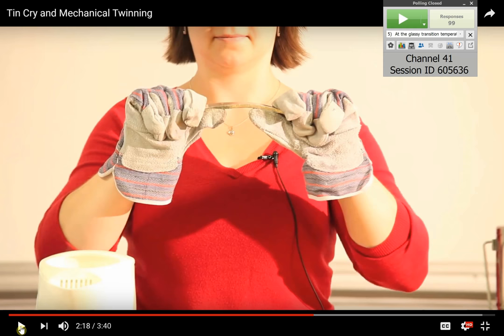So in this scenario, first off, she started by saying it's a tetragonal crystal. Tetragonal crystals don't have many slip systems, so dislocation, we know, is probably not going to be the favored mechanism. Like hexagonal, tetragonal crystals tend to twin rather than have dislocations moving. But if you heat it up and give it energy, it can achieve it. So we see evidence, and we haven't learned why yet, that at low temperatures the dominant mechanism of deformation is twinning, and heat it up, and the dominant mechanism switches to dislocation motion. The way that we know that is by hearing it. If you had a microscope and you could zoom in on it, you would see twin boundaries in one, and evidence of dislocation motion in the other.